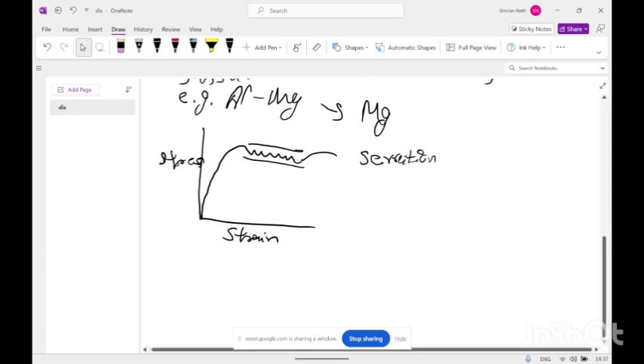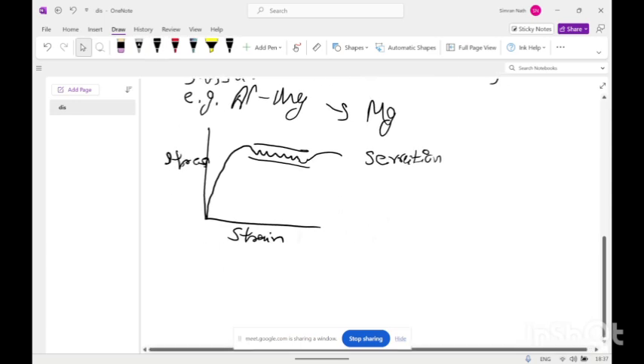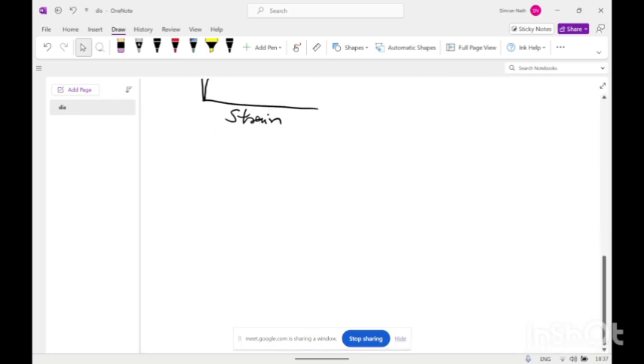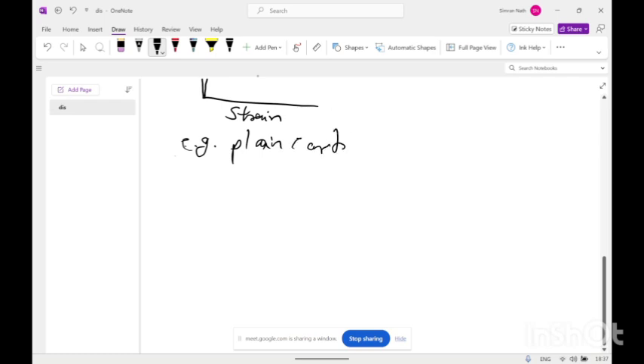And dynamic strain aging can also happen in steels like plain carbon steel. The effect of dynamic strain aging is that it decreases the ductility and toughness of the material. For example, in plain carbon steel, it happens around 225 to 375 degrees Celsius. In plain carbon steel, this is called blue brittleness.